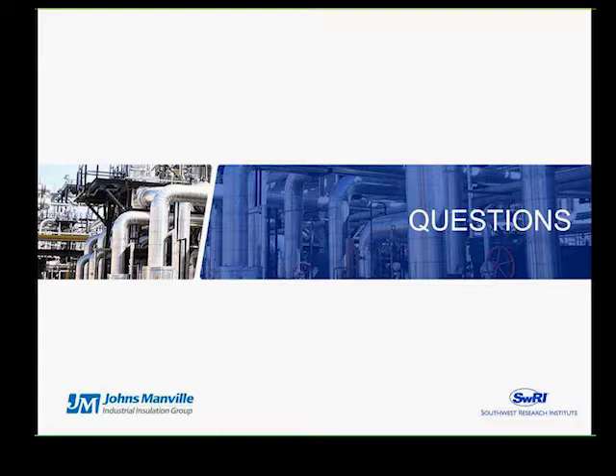All right, great. Ames, this one's for you, and that is, what is the thickness of insulations used in the test assembly? So we use 2 layers of 10-millimeter blanket for the high temperature cyclic conditions, and then 2 layers of 5-millimeter blankets for the low temperature sweating conditions. And those thicknesses were used for both the Insulthin and the aerogel blanket.